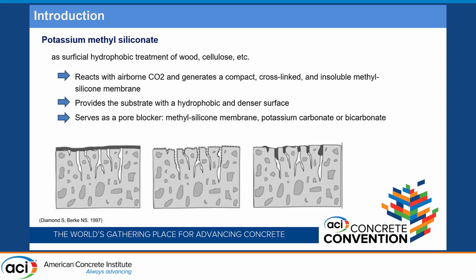PMS. PMS will react with the airborne CO2 and generate a compact film on the surface, and then provides the substrate with the hydrophobic film, and then it reacts with the CO2 and generates some products, for example, the potassium carbonate, and blocks the pores. So this one is very promising.